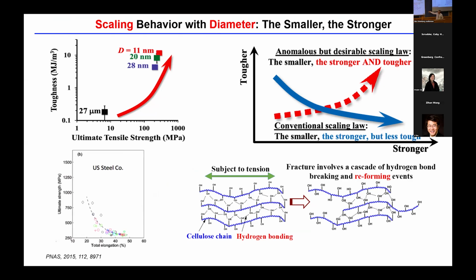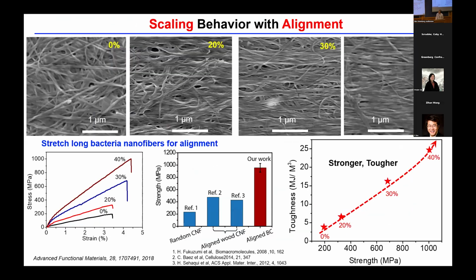I know there's some debate about whether the hydrogen bonding is the main factor, but at least the toughness and strength relationship does not sacrifice one for the other. Of course, at that time we were talking about a tensile strength of like 200 or 300 megapascal. But in the proposal, I said something like 1 gigapascal. Then we have to align the fibers, right? So how do we align them? Why do I propose 1 gigapascal?